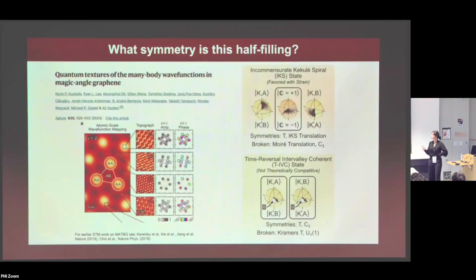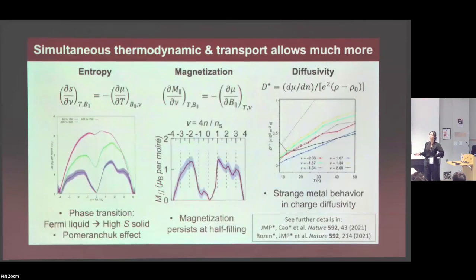And this question was also answered by this measurement actually done at Princeton in Ali's group, where they measured atomic scale imaging near the half-filling state equal to plus minus 2 states, and found this particular IKS state that has this sort of symmetry in the system. So it seems like that's also relevant for the formation of the superconductivity.